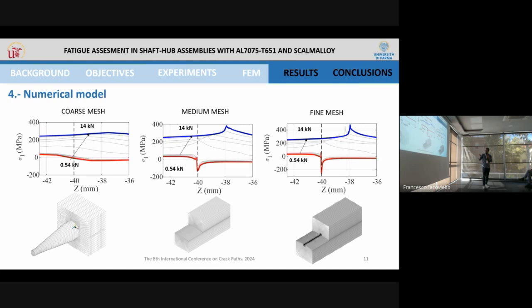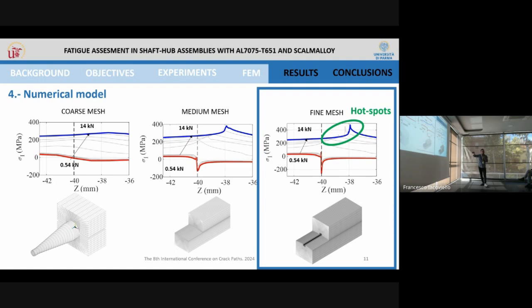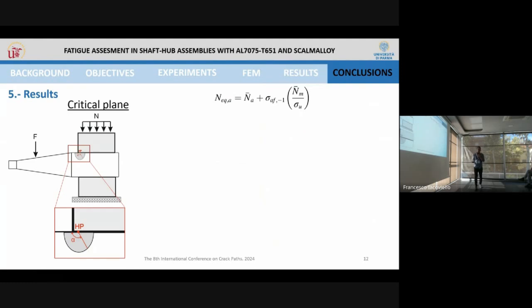Okay, so this is like an intermediate step, but we want to use this model, the finest one, to try to predict the orientation and the predicted time. The maximum points of this zone will be the hotspots for the different bending loads applied. Now, these hotspots are going to be used to estimate the critical plane. These hotspots will be at the origin of several material planes between 0 degrees and 180 degrees to cover all this area.